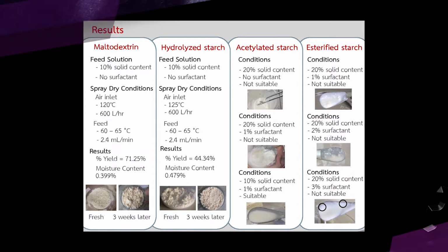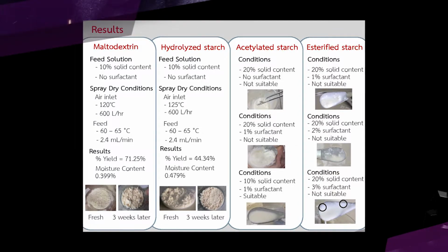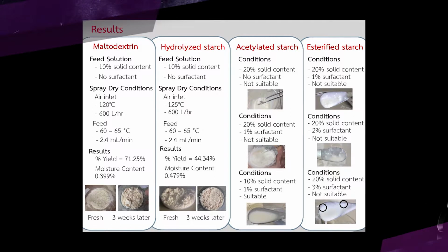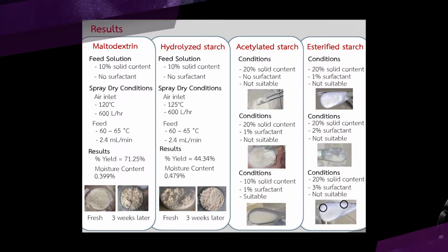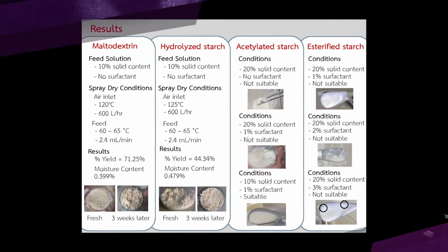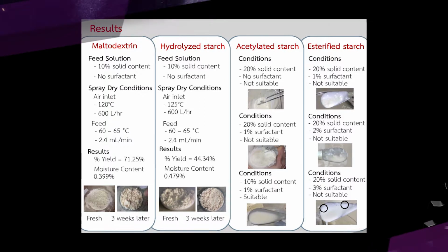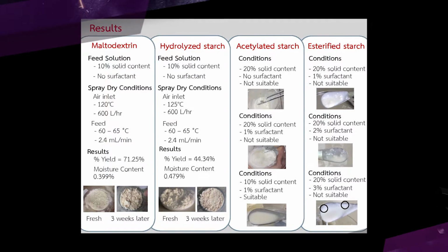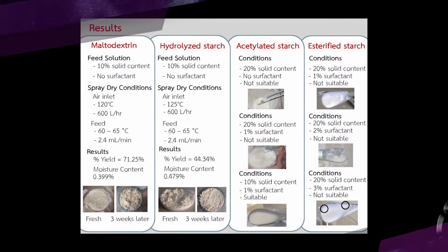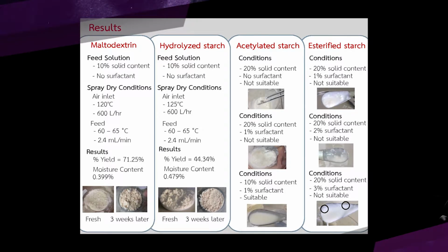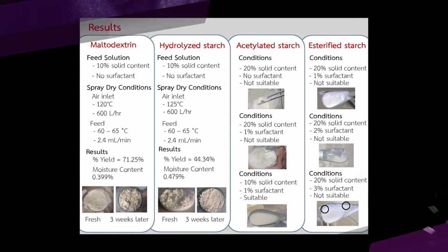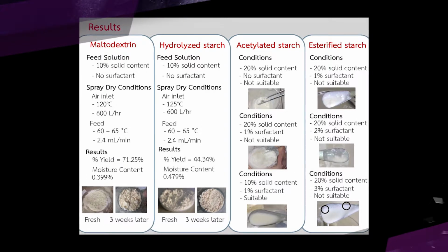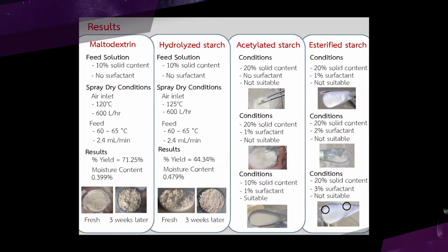For the result, the best feed solution for maltodextrin is 10% solid content with no surfactant. And here is our spray dry condition. The result that we get from maltodextrin is 71.25% yield with moisture content of 0.399%. We test the shelf life by leaving it for 3 weeks. It turned into a yellow color and the coagulate is large. However, if we break it, it's still in powder form.